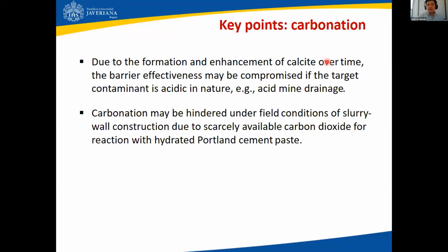So to us, the main key points and implications of this is that due to the formation and enhancement of calcite, the barrier effectiveness may be compromised if the target contaminant is acidic in nature. We all know that calcite is vulnerable to low pH conditions, to acidic conditions. So for example, if this slag CB wall is intended to encapsulate a contaminant plume from an acid mine source, we may have problems with calcite performance, or rather wall performance in the long run.